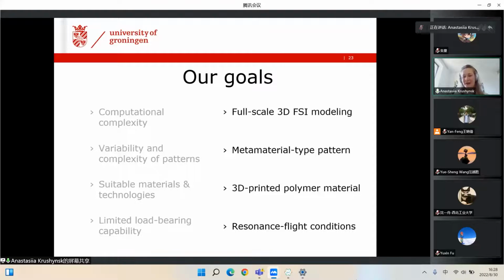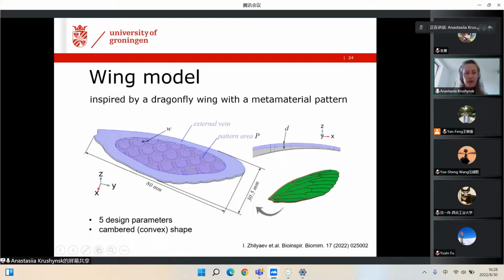So with these goals in mind, I will introduce you the model that we created, how we tested it, and how we performed the modeling. And we start from the model. So our wing model is inspired by that of a dragonfly wing. And specifically, we took the overall shape, so we preserved the shape, and we preserved the external vein of its analogue. And to keep a controllable area of the metamaterial pattern, we preserve the external wing frame from all the sides. So basically, we cover with the metamaterial only the interior of the wing. For the metamaterial pattern, we choose a very well studied, very well known honeycomb design. First, because it's simple. Second, because it allows to achieve a wide range of mechanical responses.